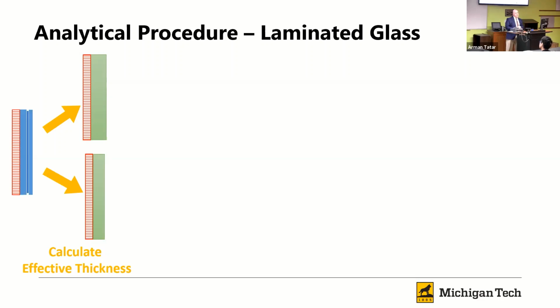So what the standard allows you to use is a fairly simplistic method, coming up with an equivalent monolithic thickness that would be representative of the laminated glass. And then we can use FEA with monolithic glass with these effective thicknesses to do our stress analysis and to check for deformation. So I have over on the side here an asymmetric laminated piece of glass, and with that we would expect our two effective thicknesses to be different, and then we would perform that stress analysis.